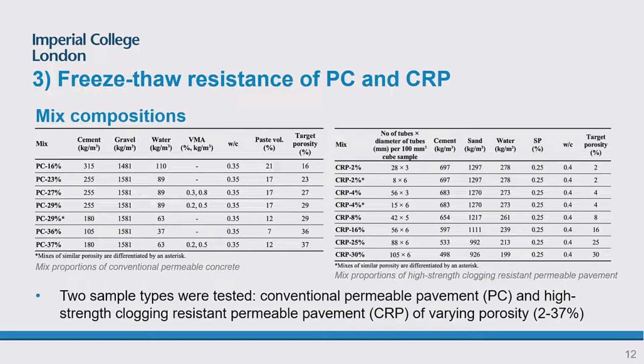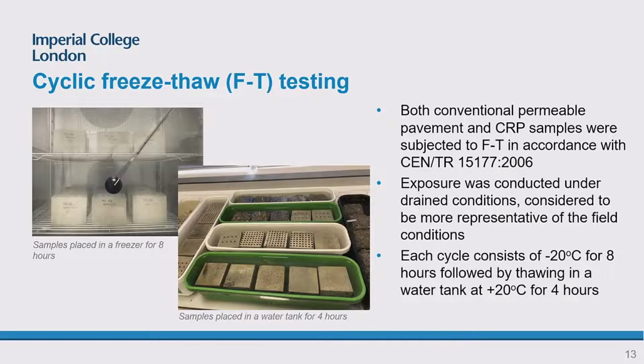So as I mentioned before, the focus of today's talk is going to be freeze-thaw resistance. So these are the samples we tested for the conventional permeable pavements and CRP in the lab, just to look at how the freeze-thaw performance compares. So we followed the same procedure as is recommended in Eurocodes. So we exposed both types of samples of different porosity to 56 cycles of freeze-thaw. So that meant 8 hours of freezing it at minus 20 degrees Celsius, and then 4 hours of putting it in a water bath just to expose it to one cycle of freeze-thaw. And then we looked at the performance of both types of pavements.